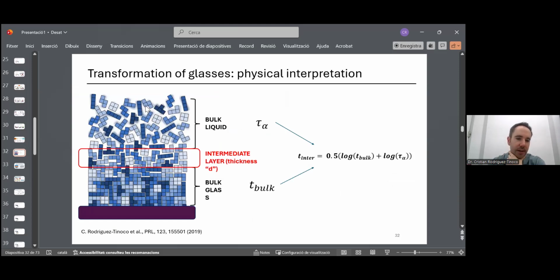So this is the glass matrix, very well packed in the ultrastable glass. This is the liquid, which is already loosely packed, and in between we have some region which is seeing the liquid on one side and the glass on the other side. So we can consider that the time this intermediate region needs to transform into the liquid state is some kind of geometrical average between the transformation time of the glass and the relaxation time of the liquid.